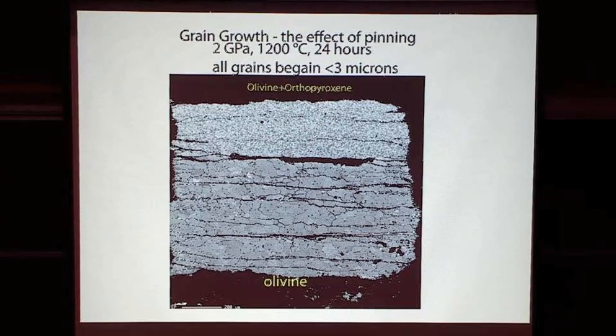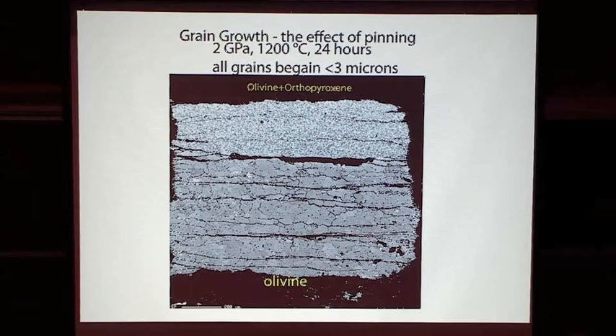Even a monomineralic aggregate can do that, because of the grain growth laws: the rate of grain growth decreases exponentially in size. But actually, this is really fast. I haven't done the calculation of what sort of grain growth you would end up with. This is 200 microns in 24 hours, and it's not even that hot. If you give me 1 billion years, I'll make really big crystals out of this material. I wouldn't be surprised if you'd make meter-sized crystals.